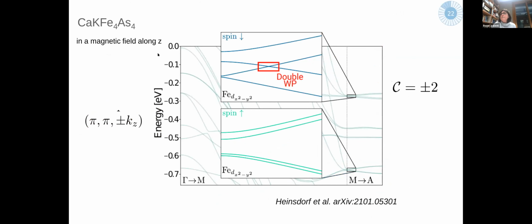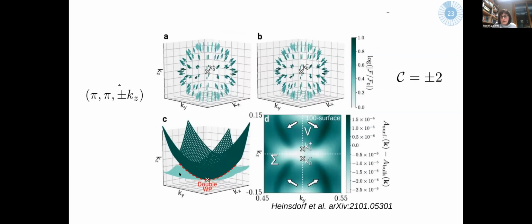So now we go to the real system and do the calculations, and we apply the magnetic field along the Z direction so that the polarized iron has a magnetic moment of about 0.6 mu Bohr. And by doing this calculation, what we find is indeed that we get a double Weyl point along this line, at plus kz and minus kz. In order to show you that it is indeed a double Weyl point, as the symmetry analysis is telling us, we analyze the band structure near this point. It is indeed a band touching, which is quadratic in the kz-kx plane, quadratic along ky-kz, and linear along kz.